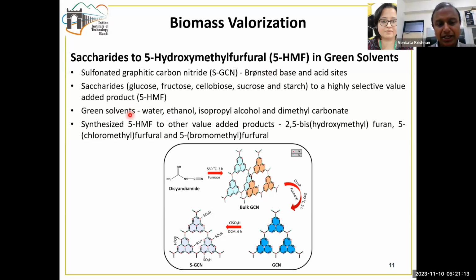And we have done all the reactions under green solvents like water, ethanol, isopropyl alcohol, and dimethyl carbonate. We have explored the different green solvents for this reaction and found that water is giving the best result. And finally, the synthesized HMF was converted to other valuable products such as 2,5-bis(hydroxymethyl)furan, 5-chloromethylfurfural, and 5-bromomethylfurfural.